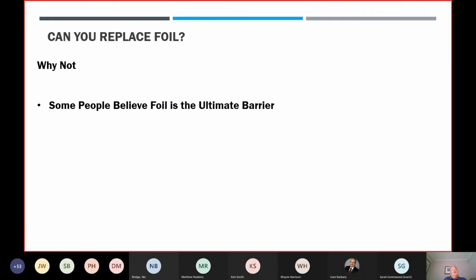Can you replace foil? Why not? Some people believe foil is the ultimate barrier. But what we actually find is it's not quite what people think, because there's been a drive to go thinner and thinner on the foil, which is driven by commodity prices. Aluminium goes up and down, and shortages and all those good things. And as you go thinner and thinner, there is more chance of rupture. There is also more chance of pinhole. So in fact, the foil is not a continuous membrane.